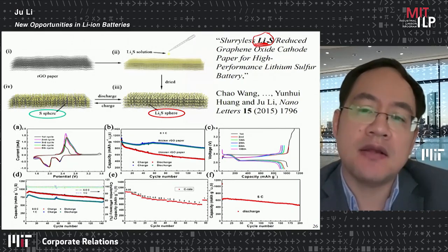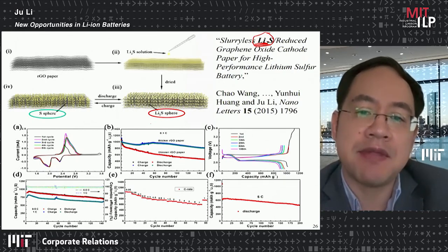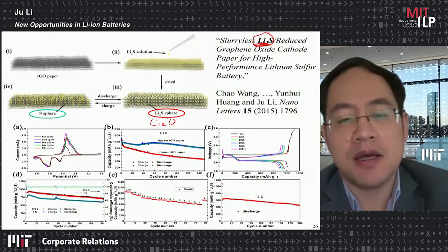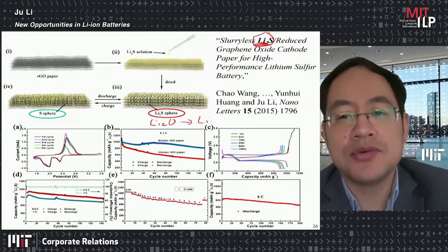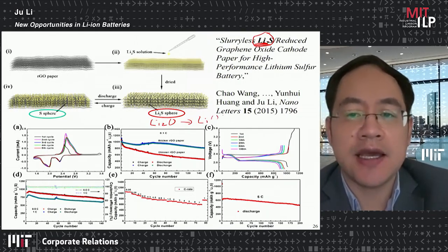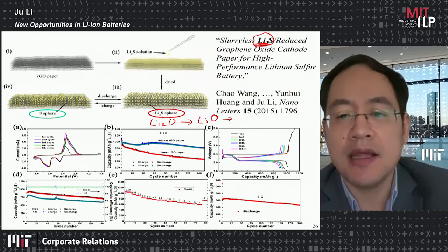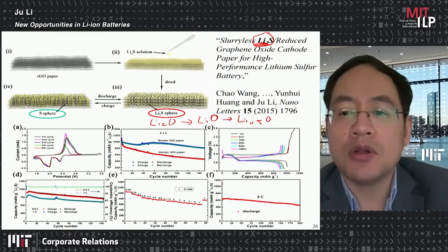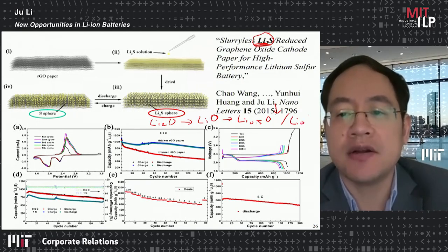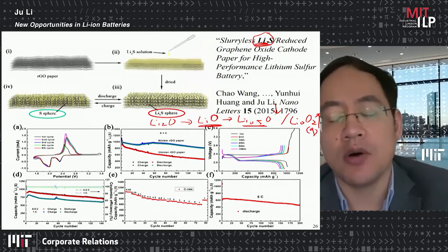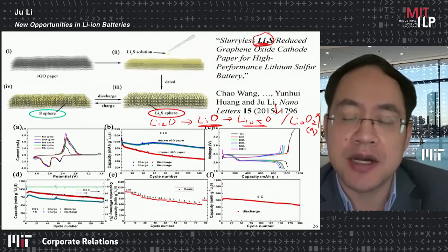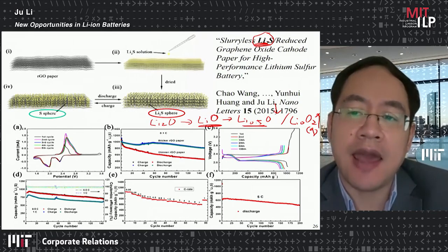So we just basically try to do the same thing for this, except that we want to start from lithium oxide and we want to basically delithiate it to lithium peroxide and even delithiate it to lithium superoxide. But what we don't want to do is we just want to stop here and we don't want to go to lithium zero, O2, because this is a gas, whereas these could still be solid or they're still dissolved in the electrolyte. So that was the idea.